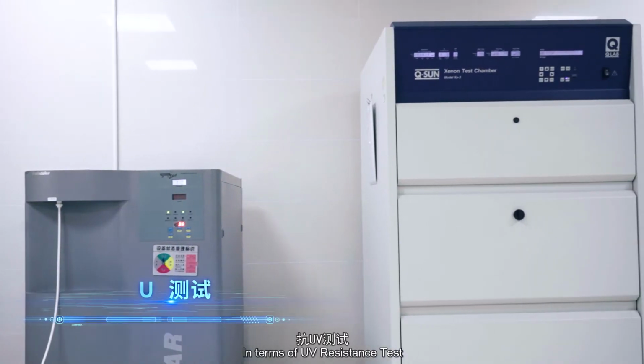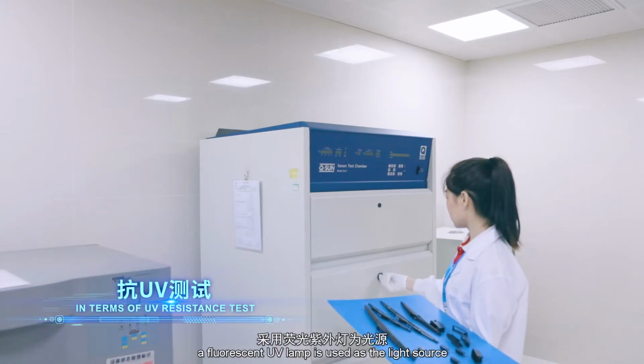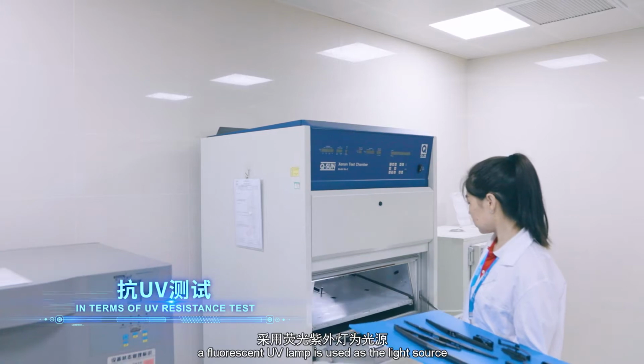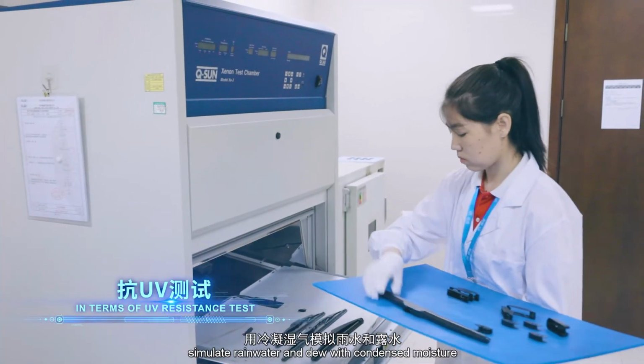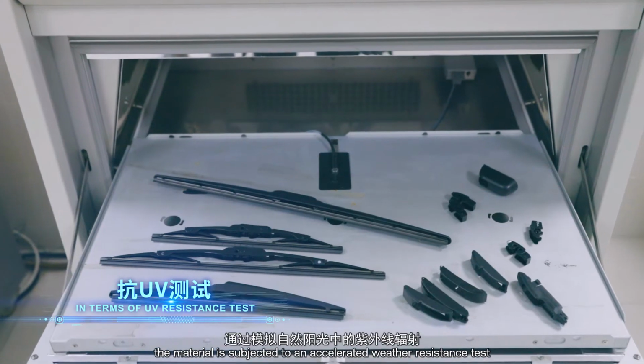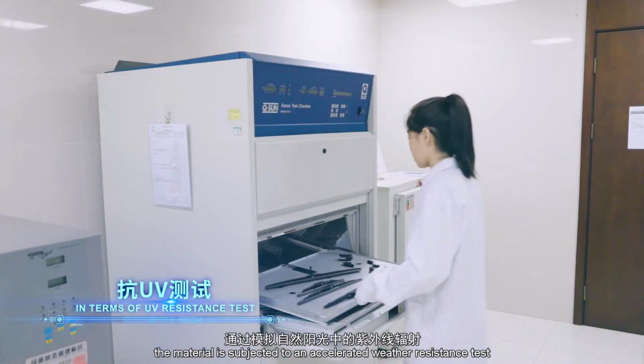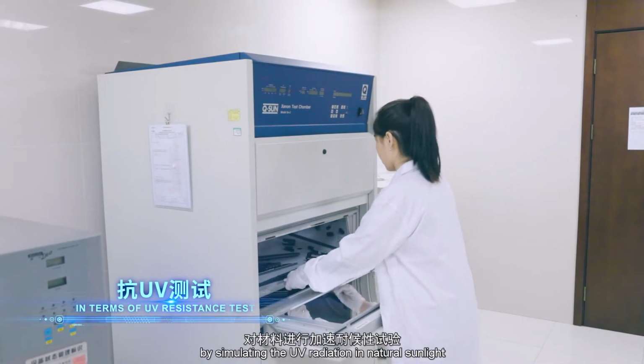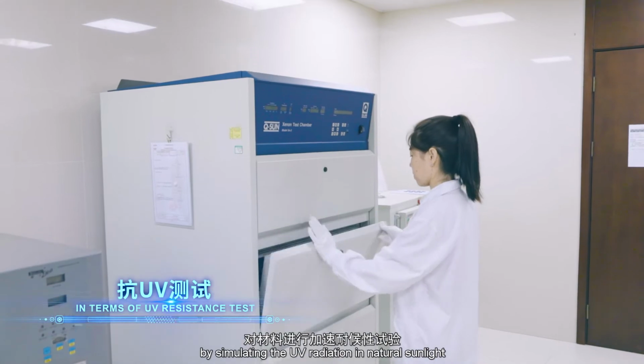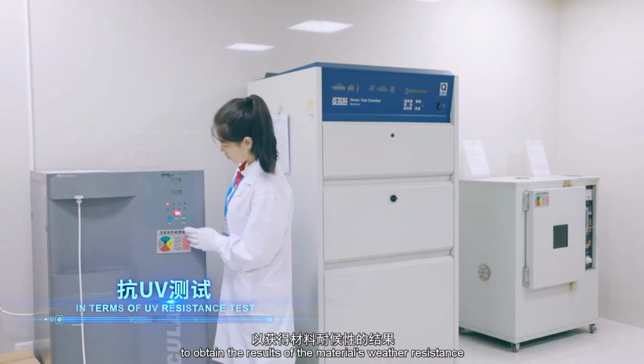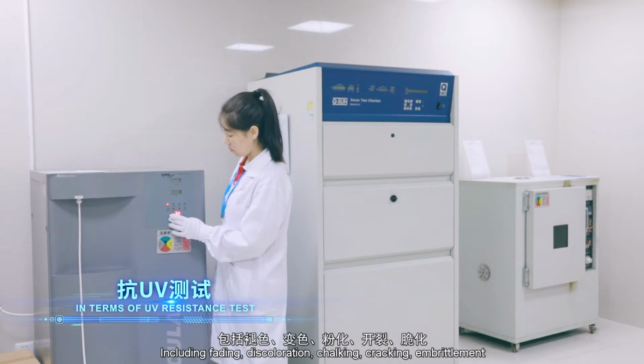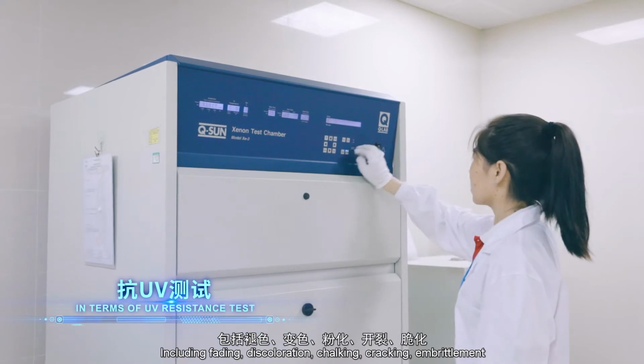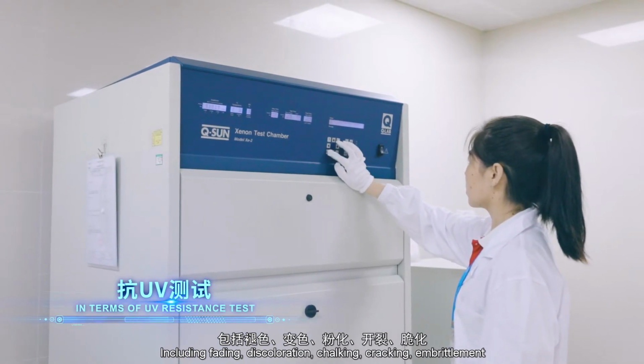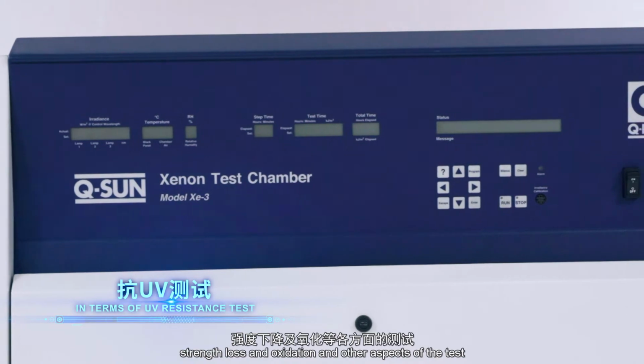In terms of UV resistance test, a fluorescent UV lamp is used as the light source. Simulate rainwater and dew with condensed moisture. The material is subjected to an accelerated weather resistance test by simulating the UV radiation in natural sunlight to obtain the results of the material's weather resistance, including fading, discoloration, chalking, cracking, embrittlement, strength loss and oxidation, and other aspects